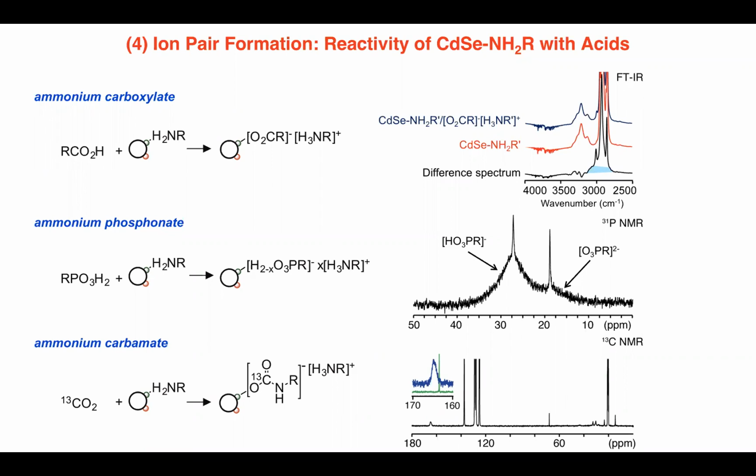So primary amines react with CO2. They do so if left on the shelf, or in our case, we actually added C13 labeled CO2 to this amine capped particle and produced this resonance out here, which corresponds to the carbamate anion. So this is problematic because most people think, I have this amine bound sample, but they don't consider the fact that their amine contains carbon dioxide. It's not well known.